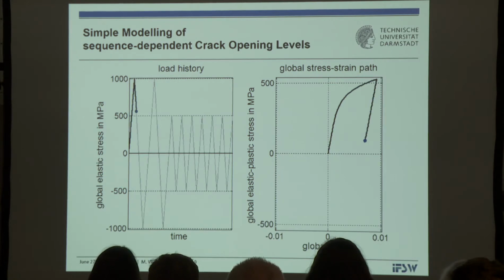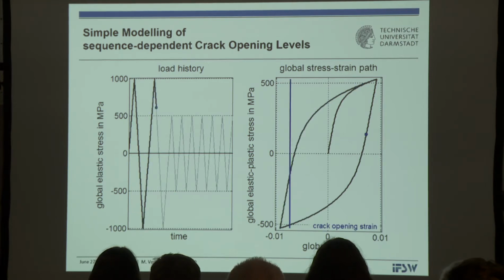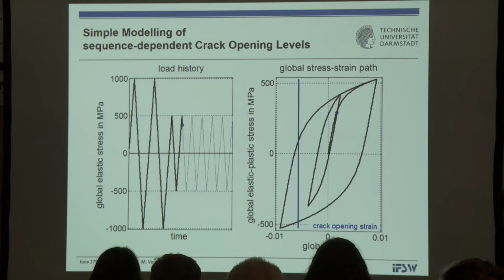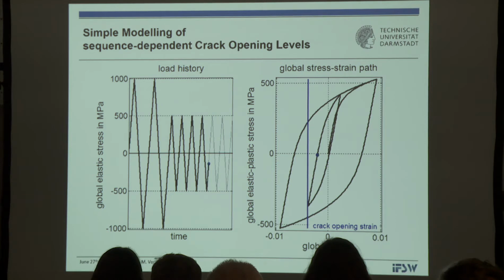And the sequence effects come in a way that, for example, here in this animation, there is a large cycle. This large cycle determines where the crack opening strain is positioned. And if you have this large cycle followed by smaller cycles, these hysteresis loops, then these hysteresis loops produce new crack surface, and this new crack surface can move the crack opening strain more or less slowly or quickly, and this has to be determined to a position which is associated with the smaller cycles themselves.